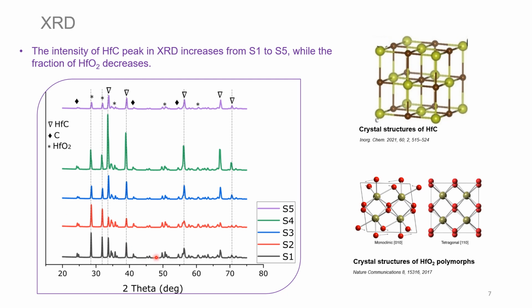Here, samples S1 and S2 were cured at 105 degrees centigrade for 1 hour and 4 hours respectively, and moisture would still be present in these samples after curing. The samples were transferred from the glove box to the furnace for pyrolysis, and the intense monoclinic hafnia phase in these two samples could be attributed to the hydrolysis reaction during transfer in air.